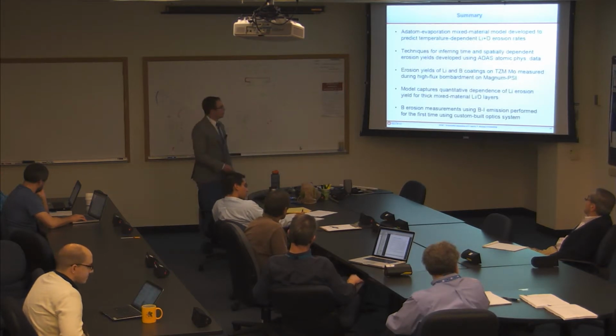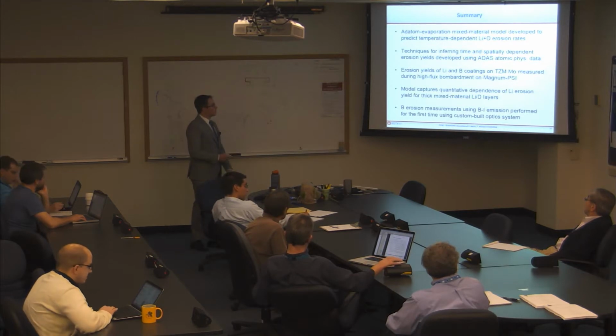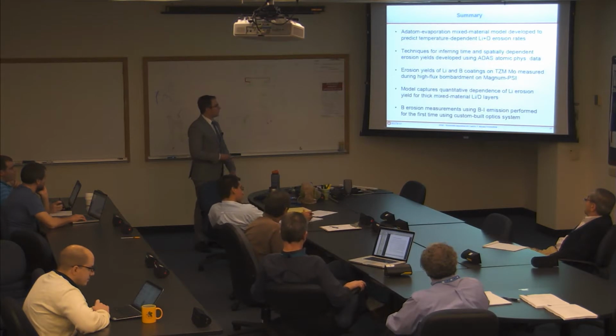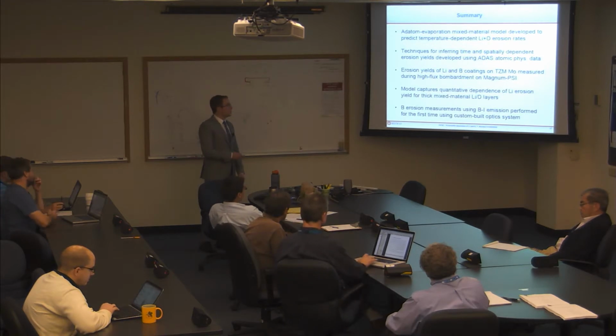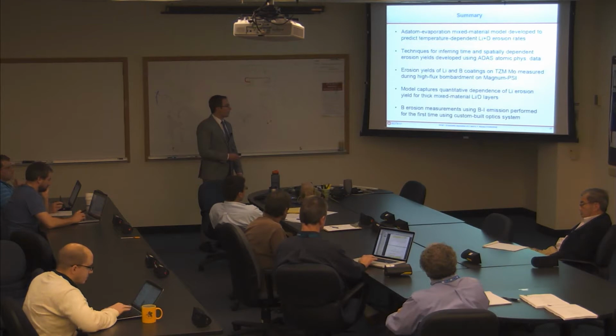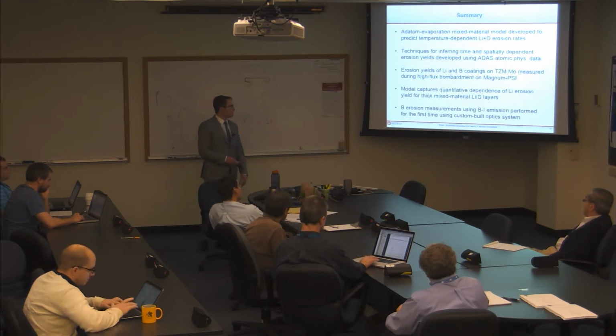All right, so summary. I developed this adatom evaporation mixed material model using a lot of existing data and some new data to predict the temperature-dependent lithium-deuterium erosion rates. And then I developed techniques for inferring the time and spatially dependent erosion yields of these mixed material films using ADAS atomic physics data. I then measured the erosion yields of lithium and boron coatings on TZM molybdenum during high-flux plasma bombardment. The model was observed to capture the quantitative dependence of lithium erosion yield, at least for the control case of neon and the thick mixed material lithium deuterium layers, and the boron erosion measurements, which I didn't show you.